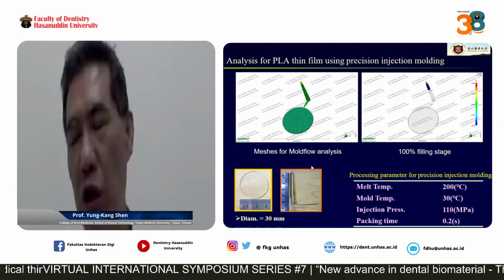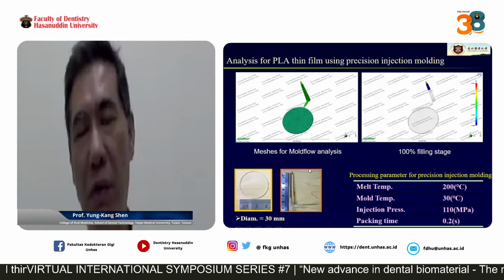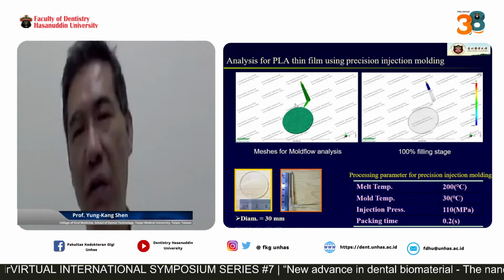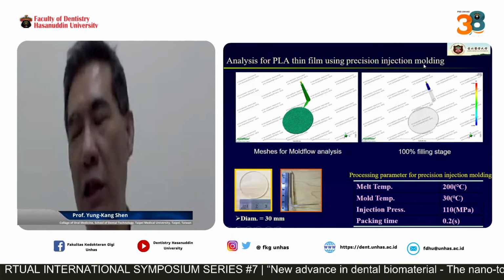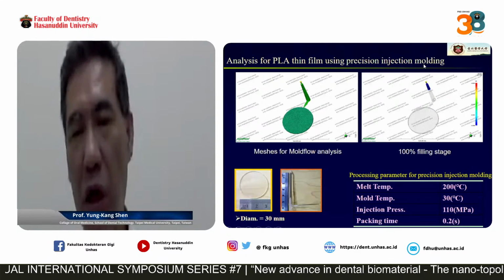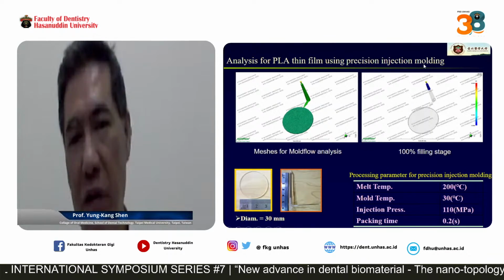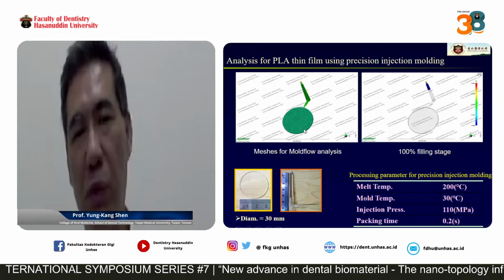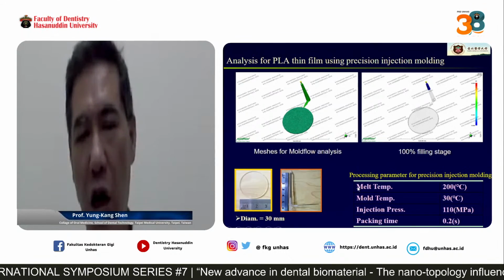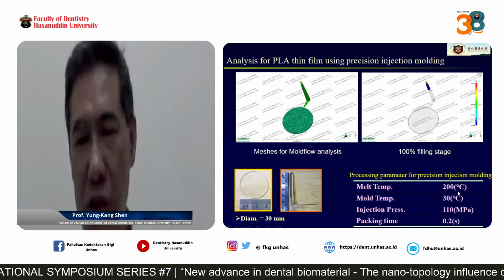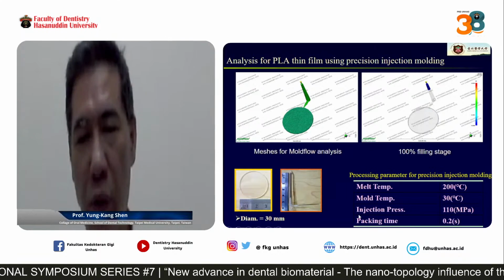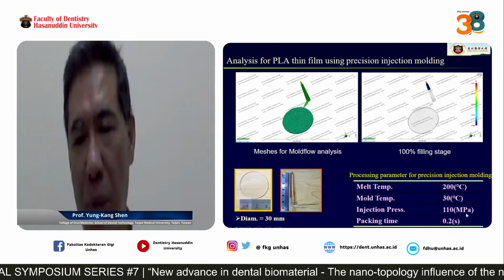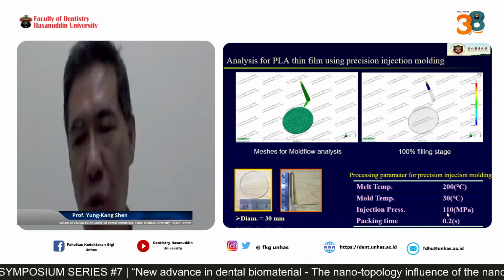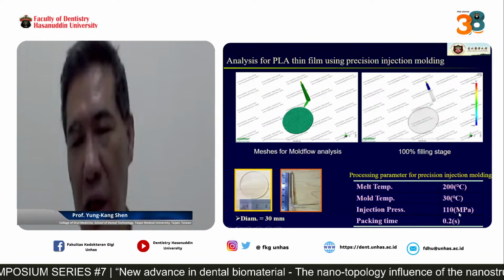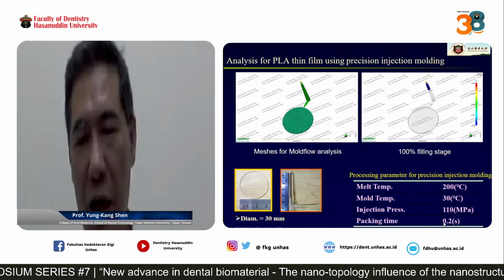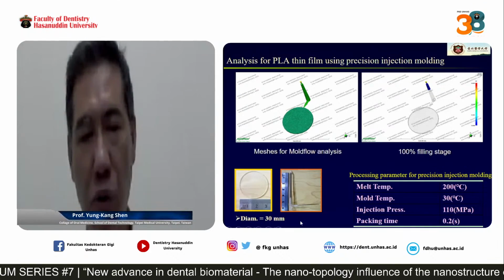So in here, we use the mold to make the polymer thin film. To make this polymer thin film, we use injection molding and manufacture the mold to produce the polymer thin film. This is the mold flow simulation for the injection molding. We use melt temperature 200 degrees C, mold temperature 30 degrees C, injection pressure 110 megapascal, and the packing time of 0.2 seconds.